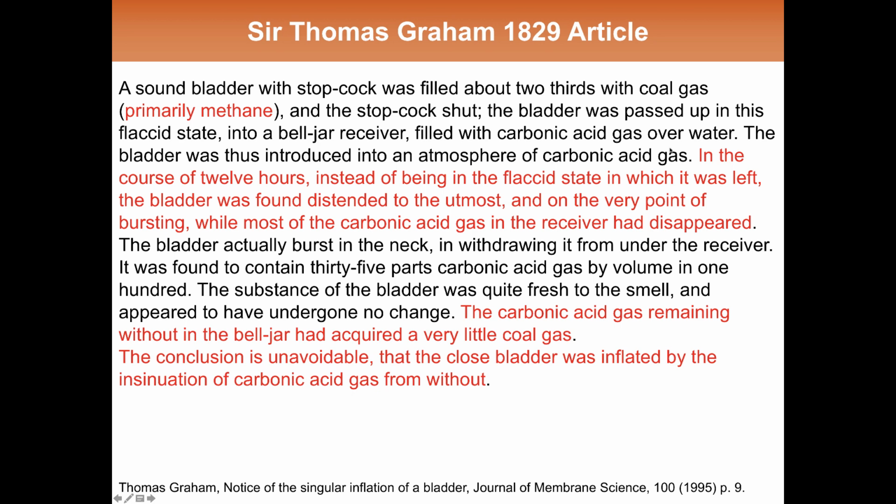Now, we know today that carbon dioxide transmits through polymers always much faster than methane. CO2 is a smaller molecule and it has much higher solubility, and so this is another case that harkens back to the Abe-Nollet experiments and some of Mitchell's experiments.